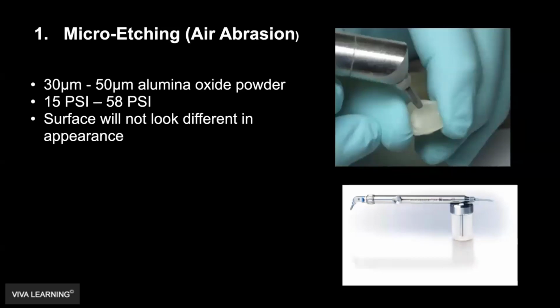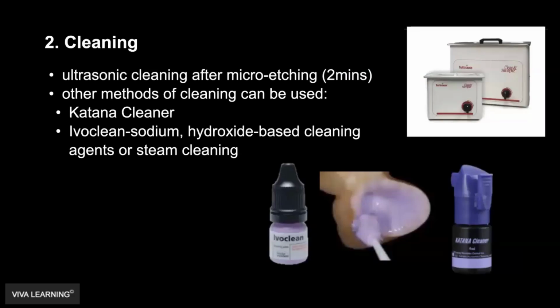So how do we do it? It's 30 to 50 micron aluminum oxide powder, and we go on the internal surface very quickly and get that sandblast. It's the inside, the intaglio surface of that crown, and this will not look any different. The thing that we also do is we go ahead and clean it, and the way that we clean